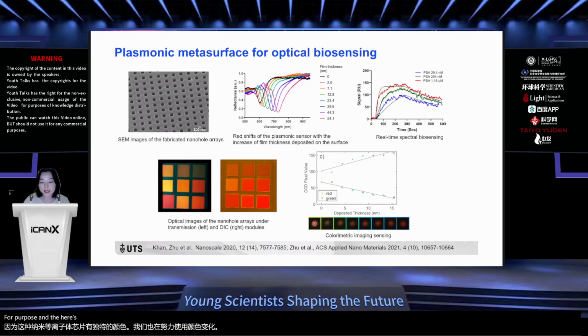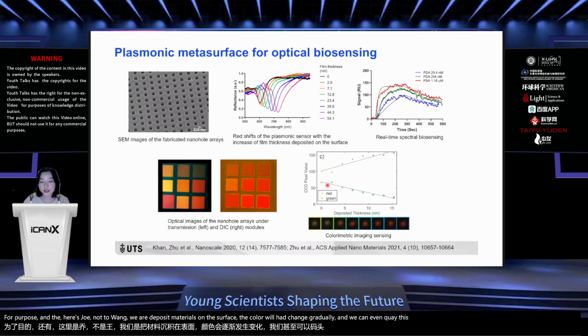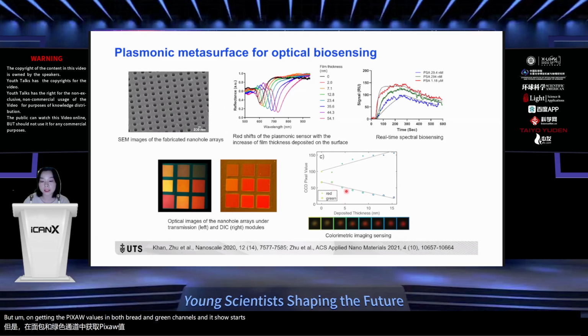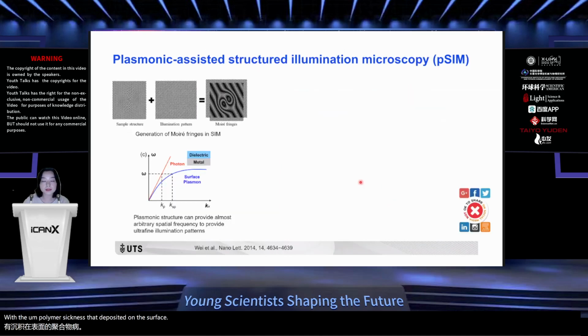And here shows that when we deposit materials on the surface, the color will change gradually, and we can even quantify this change by getting the pixel values in both red and green channels. And it shows that the pixel value actually has a linear relationship with the polymer thickness that is deposited on the surface.